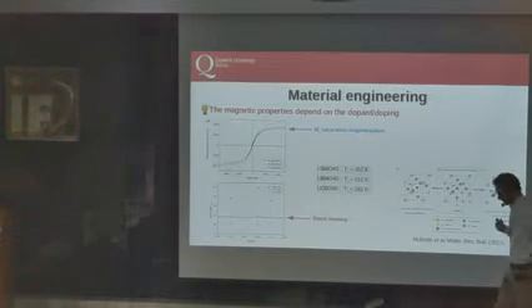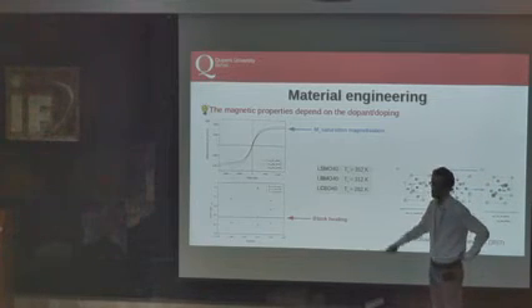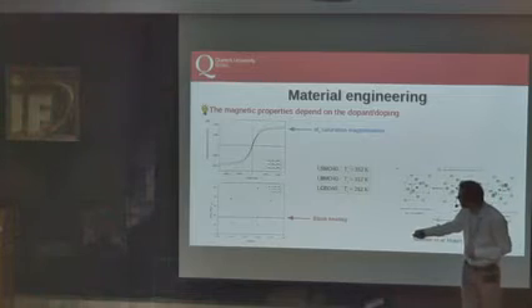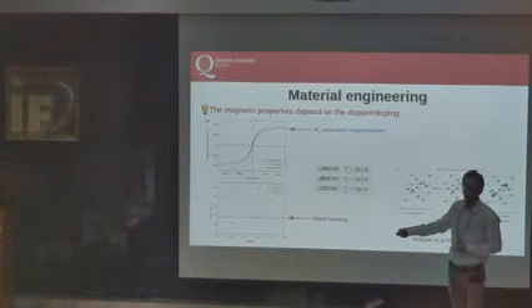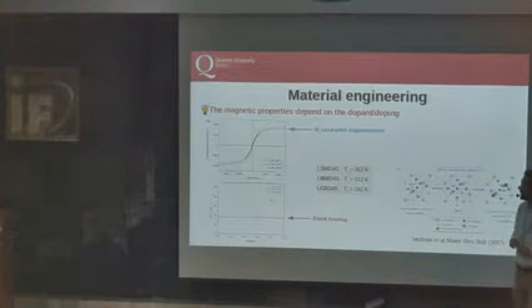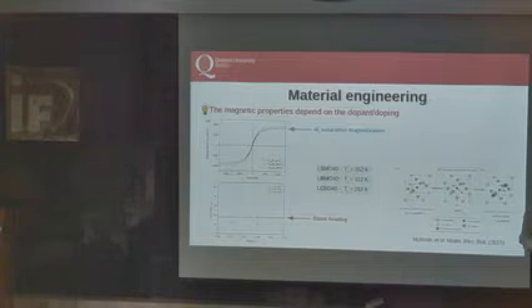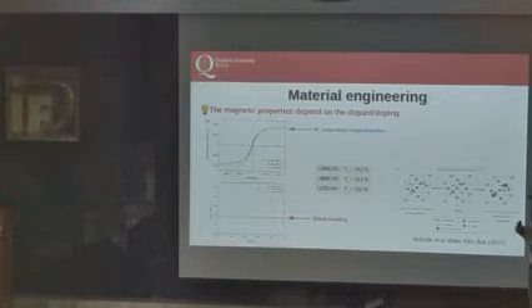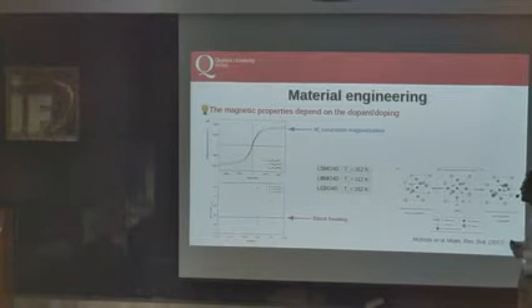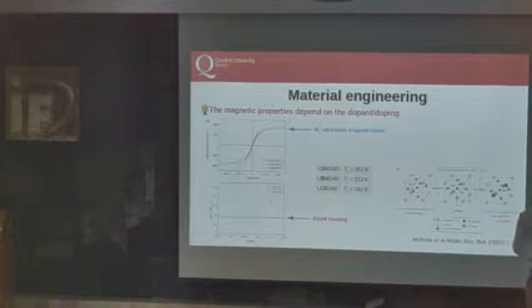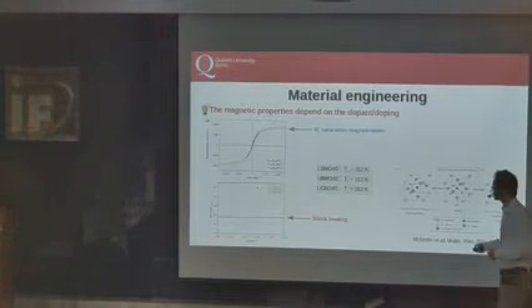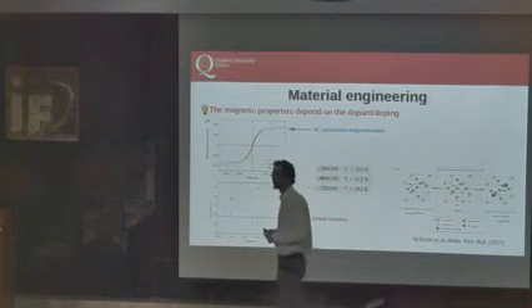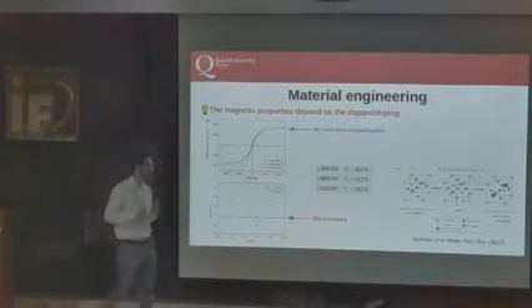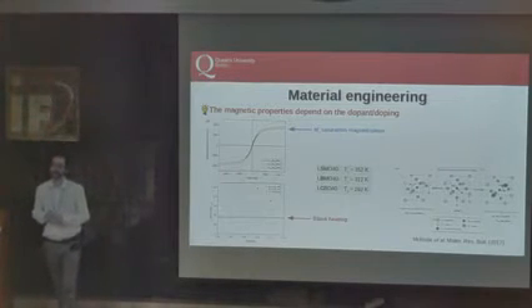So let's see the heating power. This again is usually measured in SAR, specific absorption rate, and I hope you can see it is watts per gram of manganese. This is what you find in the articles. And this is part of the hard part of experiments. If you just measure with your thermometer a vial of purified water and no magnetic nanoparticles, there is a little increase of temperature. This is called the blank heating. This is due probably to either eddy currents in the liquids, or most likely some dispersed infrared radiation.